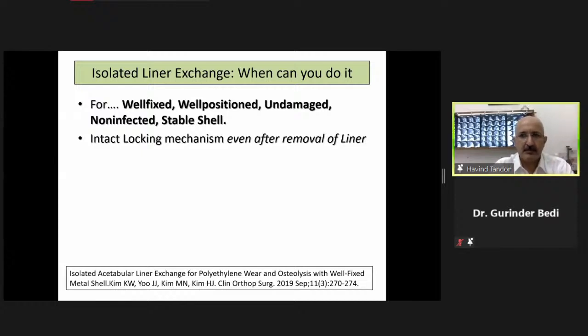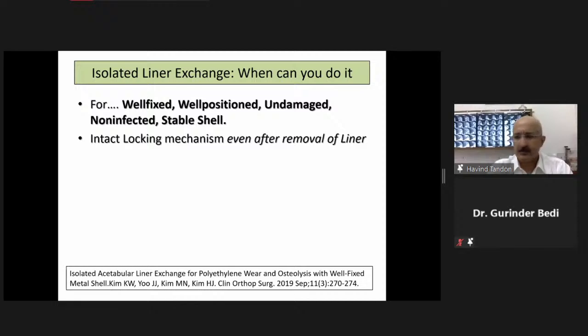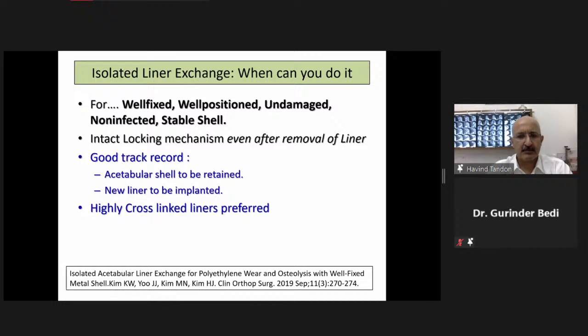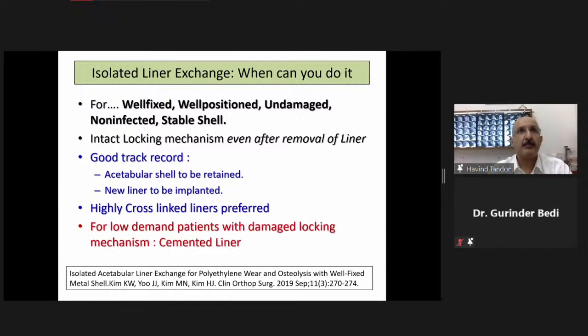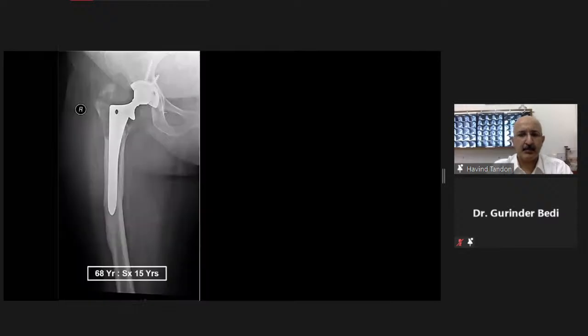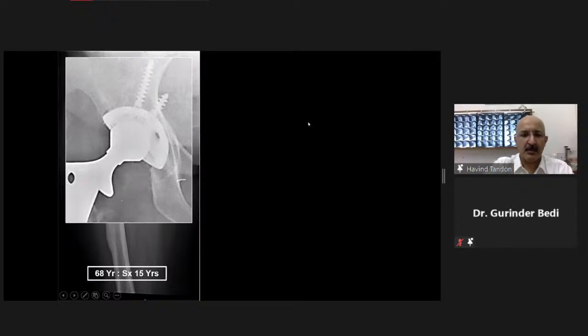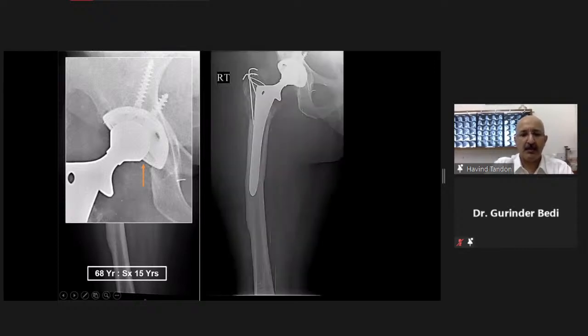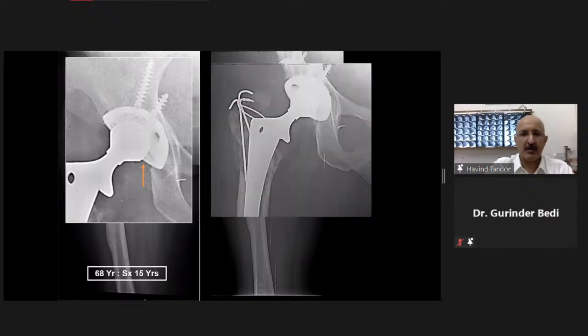Sure, sir. So, isolated liner exchange can be done for a well-fixed, well-positioned, undamaged, non-infected, stable shell. We still have the interlocking mechanism after removal of the liner. And you should be sure that the kind of components you are going to use have a good track record. In case of a low demand patient with a damaged locking mechanism, one can safely use a cemented liner. One example, a lady operated about 15 years back came reporting with lysis and one can see that the head has moved up. There is wearing out of the inner bearing. In this case, we grafted the trochanter, fixed it, and changed the inner bearing. Liner exchange was done, and she behaved very well.